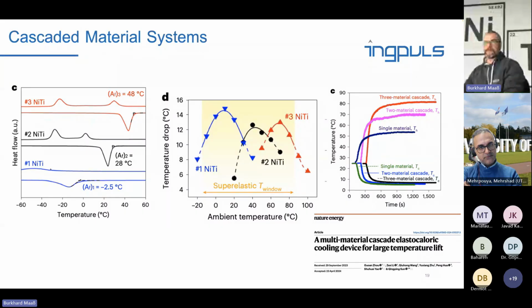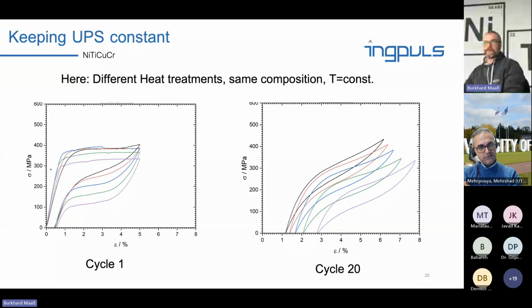So here we have a quaternary alloy, and we do different heat treatments, and we don't change the composition, and we look at the tensile curves at a constant temperature. We look at the first cycle, which is what you mostly see when you see tensile curves, but we know that the material will change after some training cycles, and then we look at the 20th cycle. And now we have a different set of heat treatments, and we try to get these at different temperatures to have an overlay. That was our goal to show here in this work.